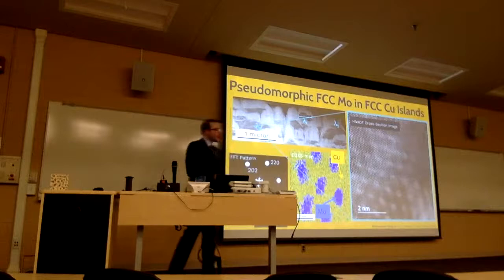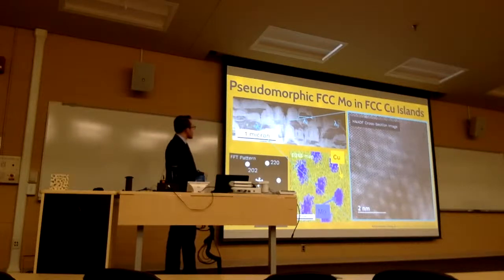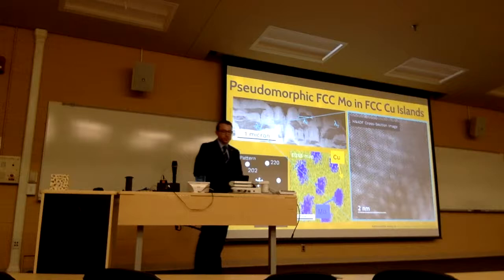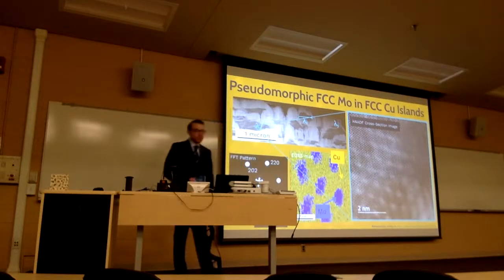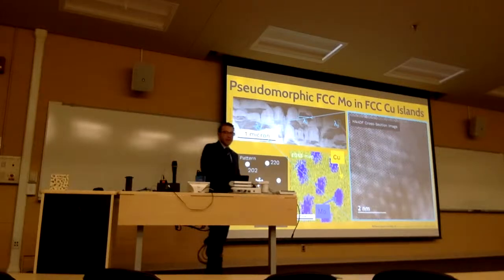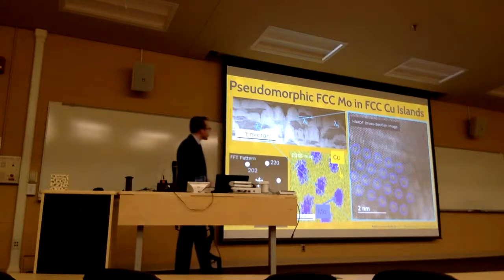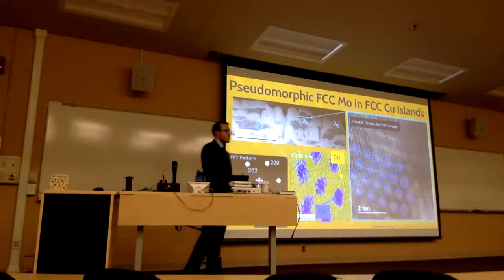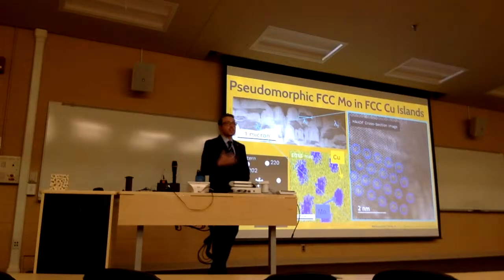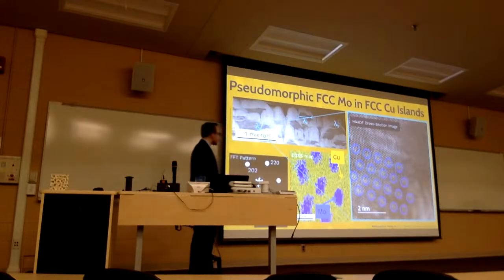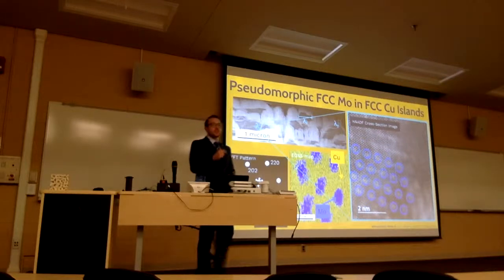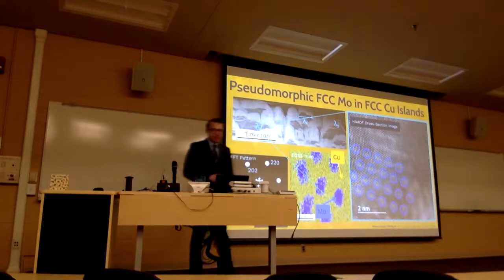If we actually blow up in higher resolution what's going on at lambda 2, what you can see is this atomic number contrast image, which shows the copper matrix behind in dark. What we started to see is actually brighter regions in this image. And I can actually highlight them here with circles, and you can see that they're very ordered and arranged in a very particular way. We chemically mapped this region of the sample. We discovered that in fact it's moly precipitates that are arranged in a superlattice inside the material.